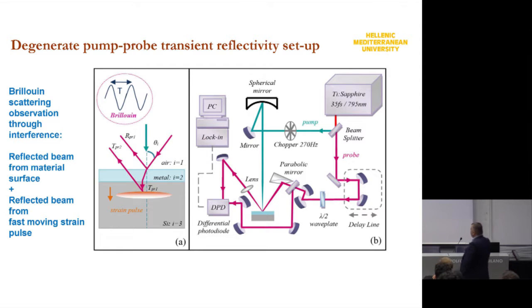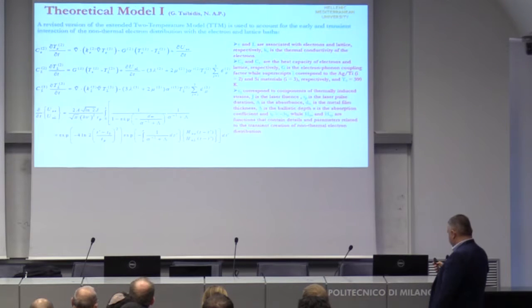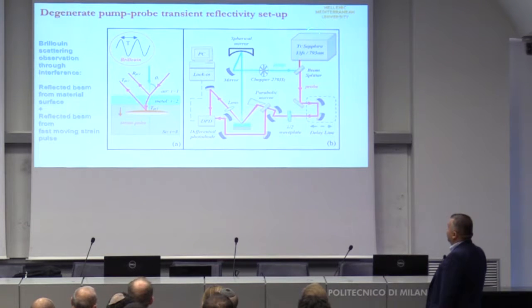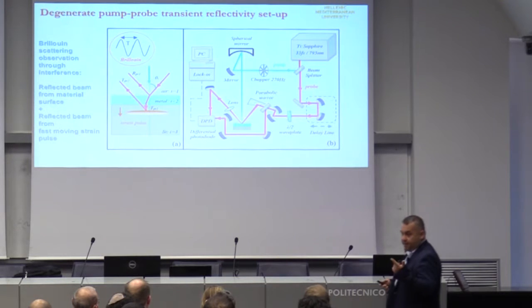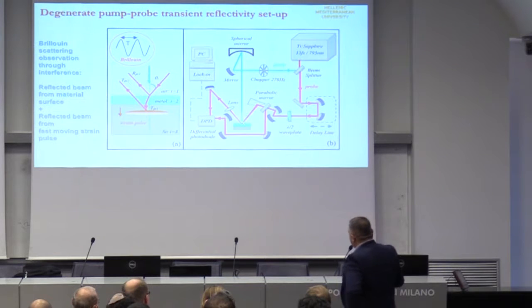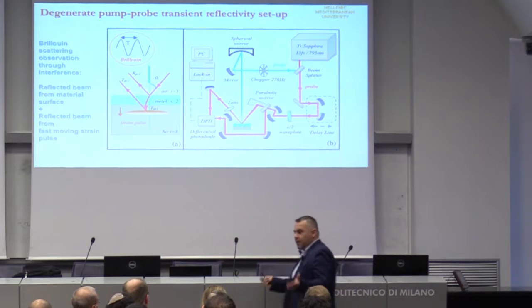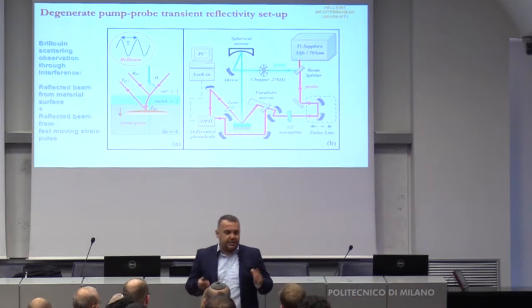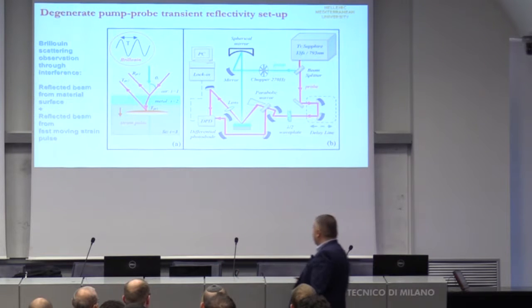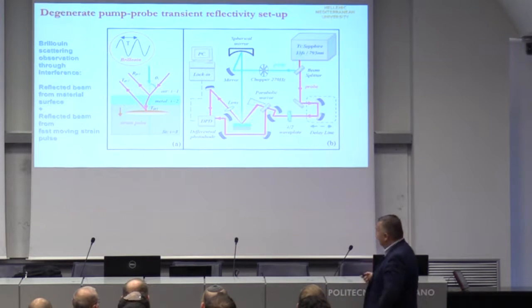Let's see a typical experiment. Here is a typical Brillouin degenerate pump-probe transient reflectivity setup. We have a femtosecond laser. We split the laser into the pump beam and the probe beam. We modulate the pump beam and not the probe beam, and then we measure the reflectivity change by differential photodiode with lock-in detection and a lot of difficult techniques that we use for signal processing. And what do we try to measure?